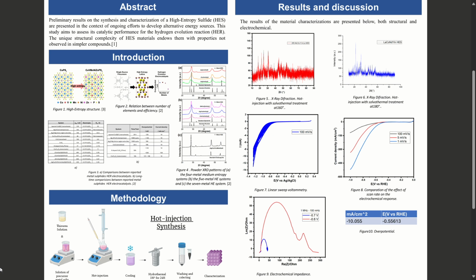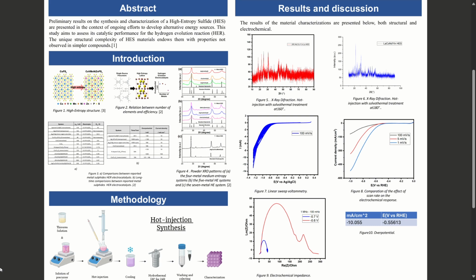Now, let me highlight the main results. Structural results. The X-ray patterns confirm the formation of crystalline sulfide phases. At lower synthesis temperatures, the patterns showed considerable noise, suggesting poor crystallinity. However, when increasing the solvothermal treatment temperature, the diffraction peaks became sharper and more defined, indicating a clear improvement in crystallinity. This means that fine-tuning synthesis parameters has a direct effect on structural quality.